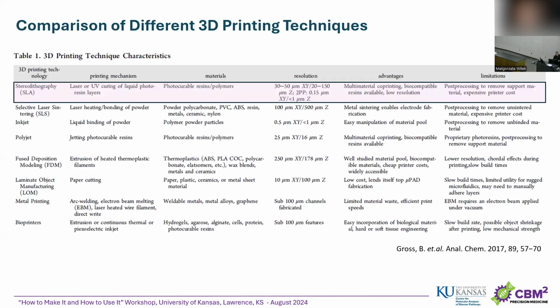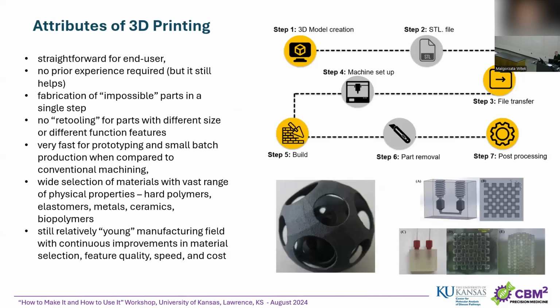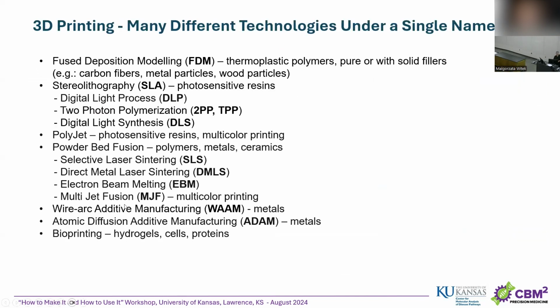So let's put it this way. If we look at, for example, this ball, this was done with multi-jet fusion printing. The technique works like all those powder bed fusions I mentioned. You have a big container with particles, for example polymer particles, a layer of polymer particles. You bring the laser that melts the plastic into one layer of your part. Then you feed another layer of the polymer particles, spread it evenly on top, and the laser comes again and really quickly produces those parts. And it goes layer by layer by layer.